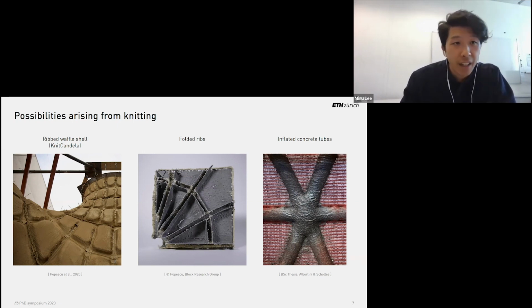Candela pavilion, where you can see really this ribbed structure, and also the cable net which runs through the ribs. In the middle, you can see that you can also create folded ribs that additionally stabilize the formwork. And then on the right side, an example of these inflated concrete tubes where we just filled up this space between the textile, and it really created this tubular frame.